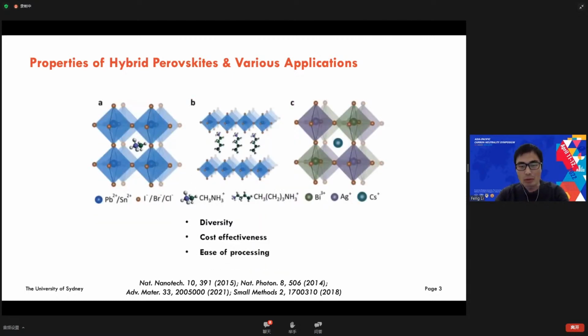This kind of material also has very high diversity. They have many different forms, and it's quite easy to tune the dimension. Currently, we already have 2D layered perovskite materials, and 3D and double perovskite materials. We can also have different forms of hybrid material, like single crystals, polycrystals, quantum dots, and nanostructured materials. And it's quite easy to fabricate and grow this kind of material. We usually use the solution process method to prepare them.